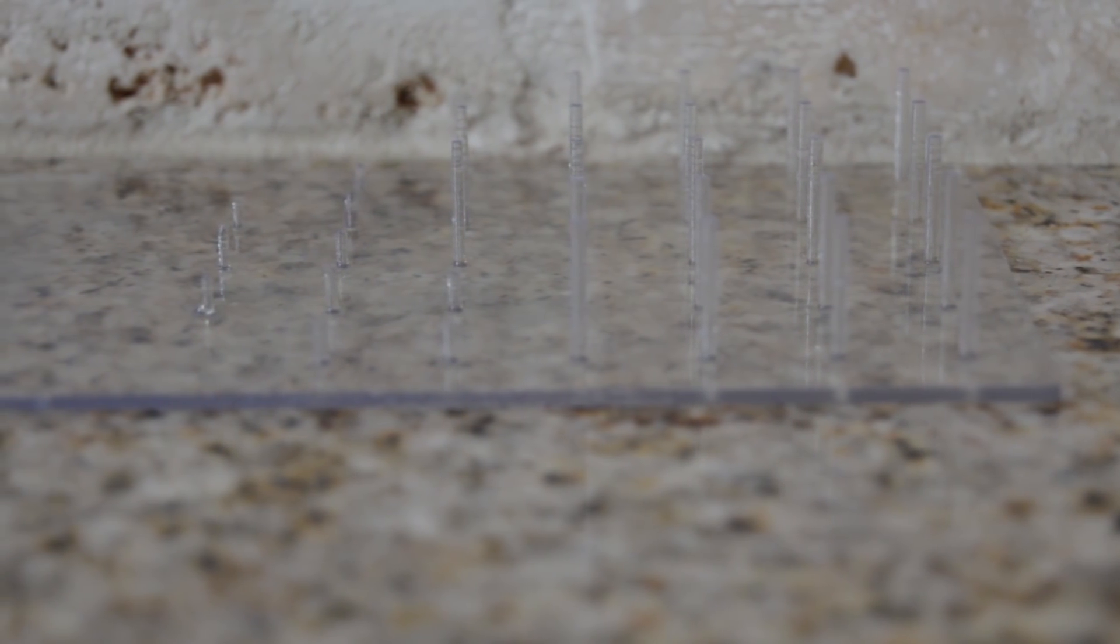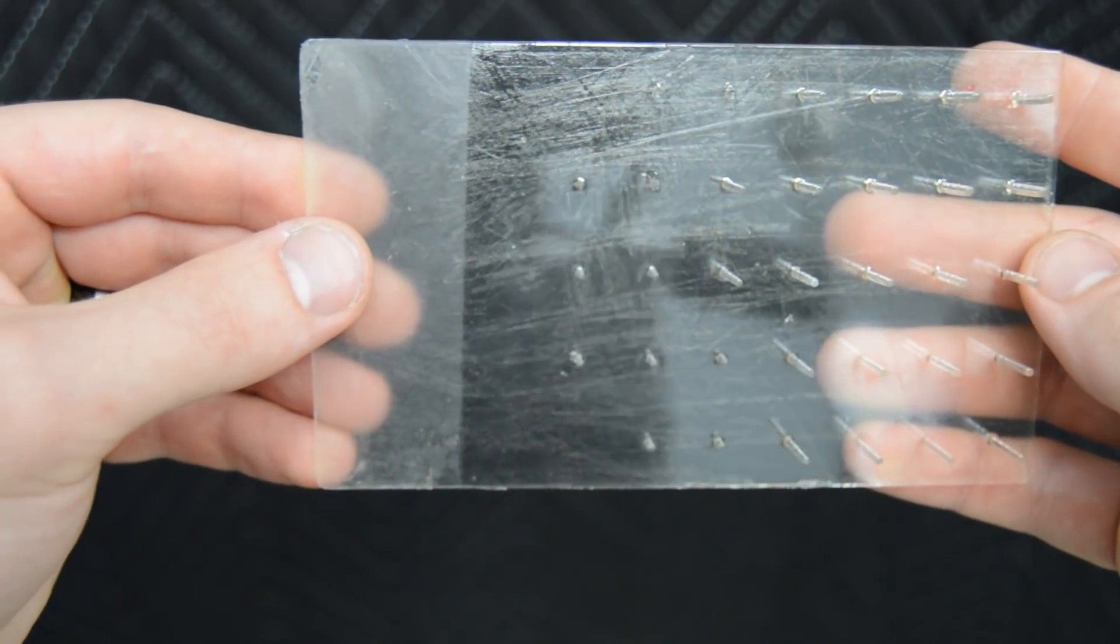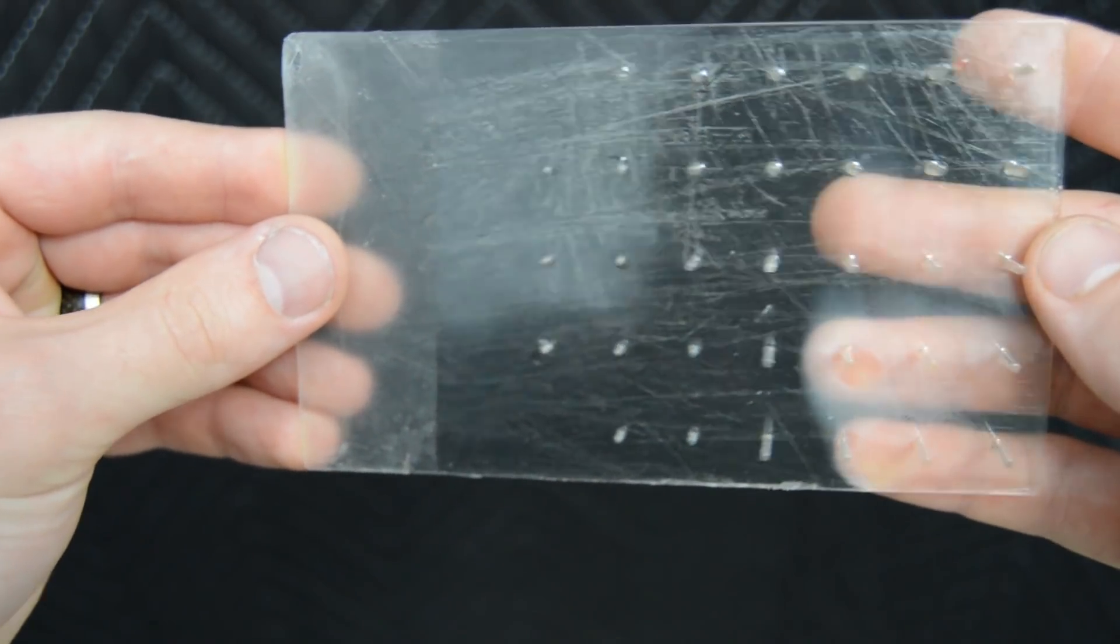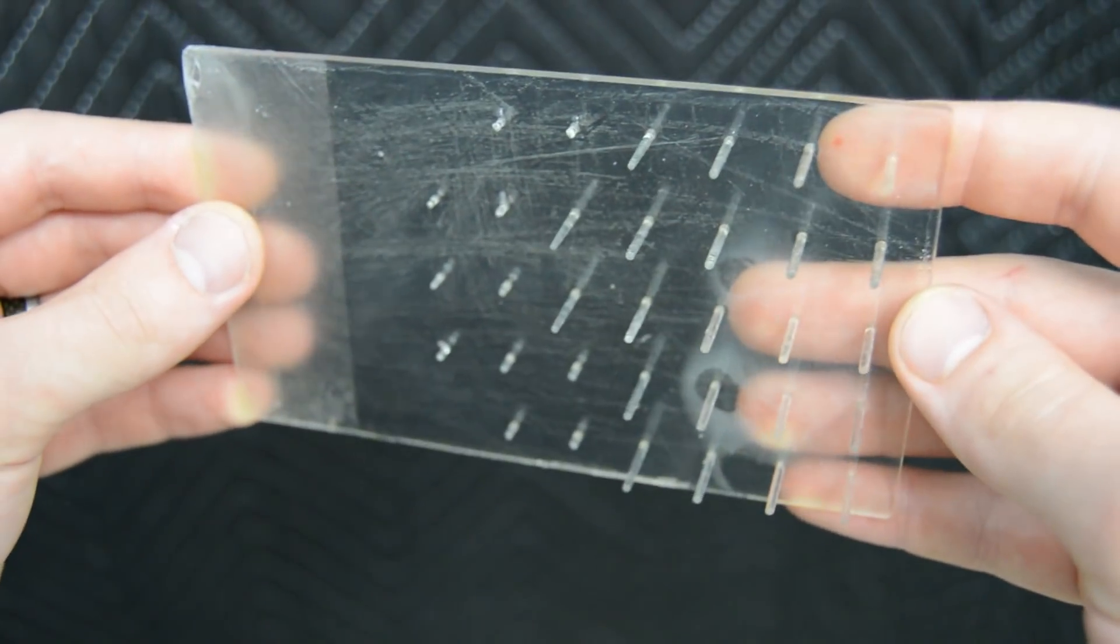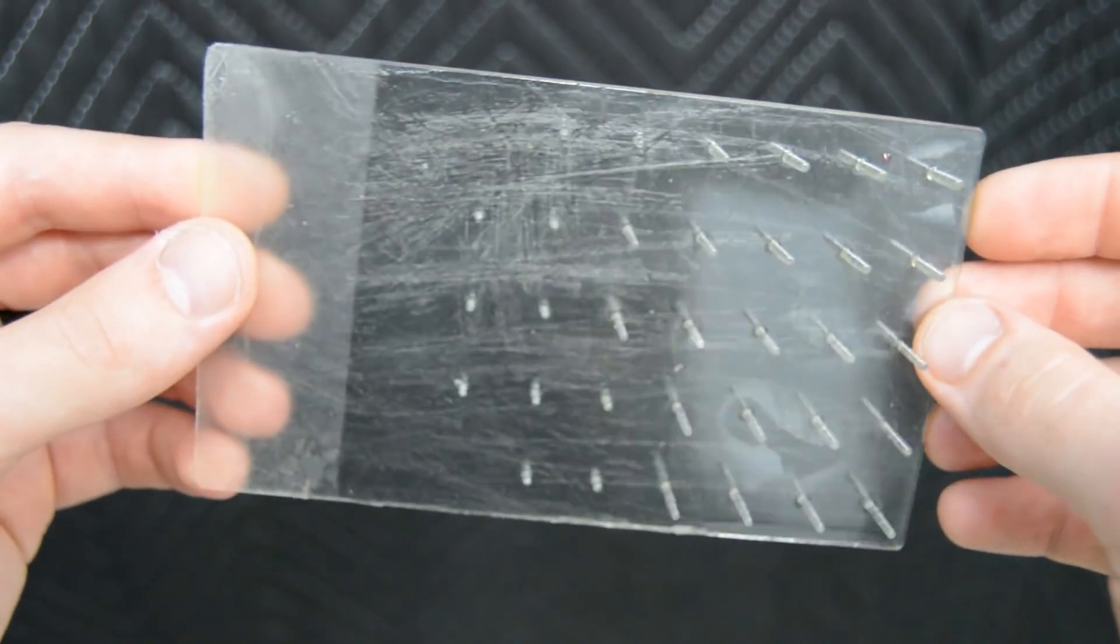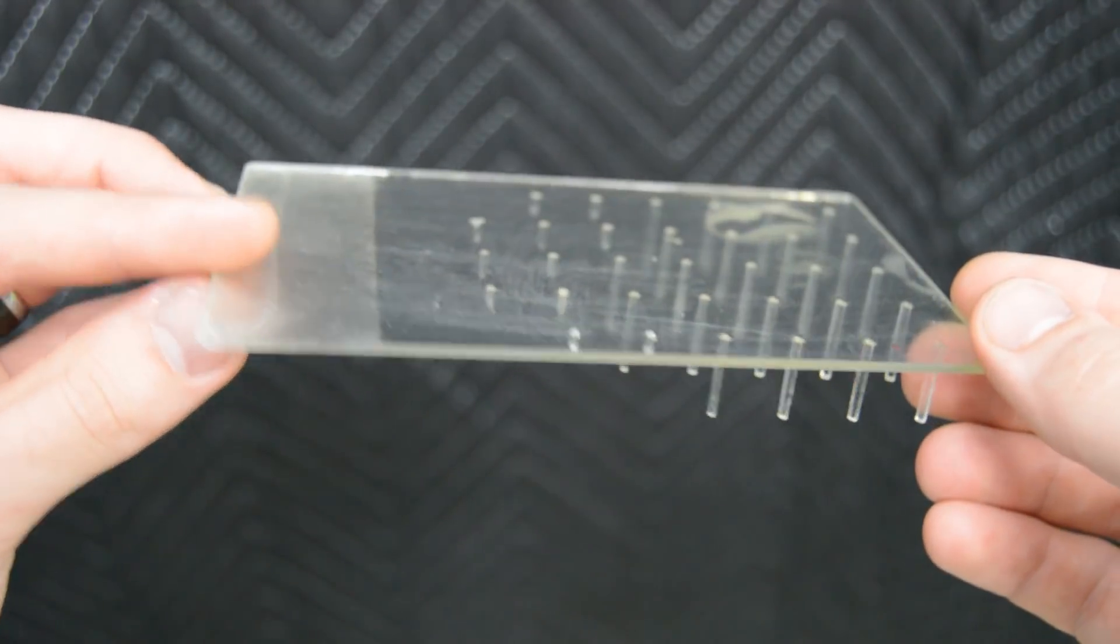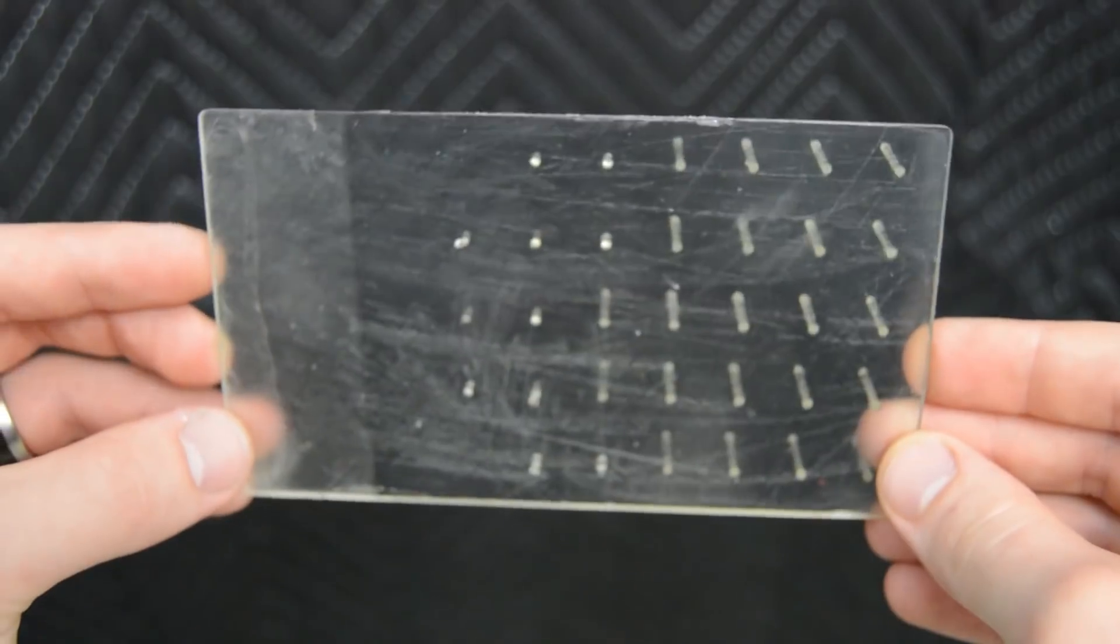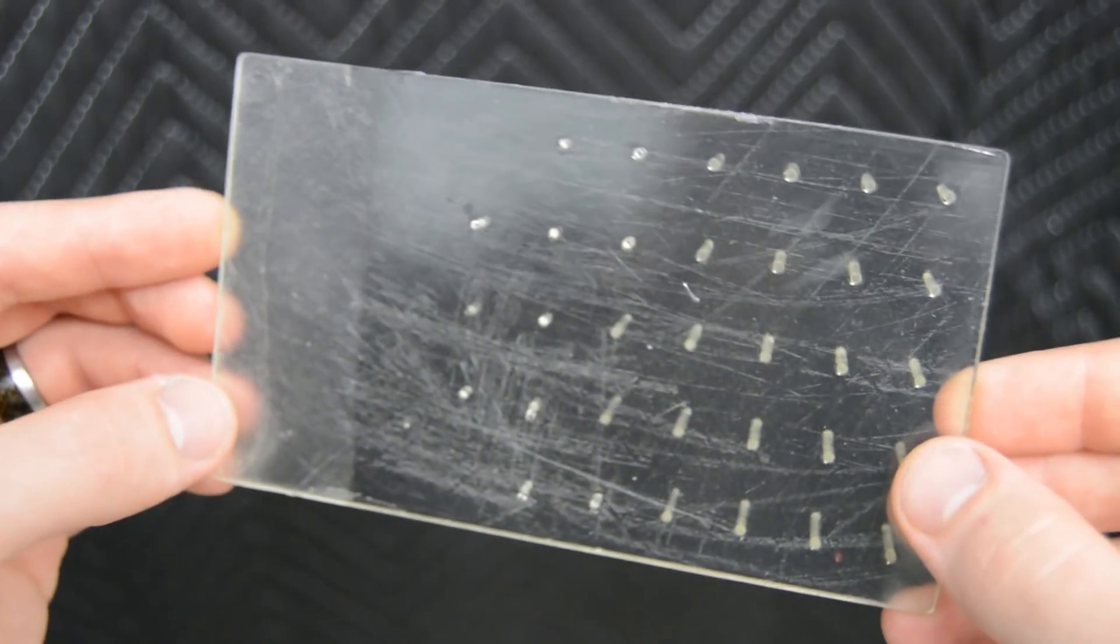What you'll see is that I dipped about 80% of it in the polycrylic and it came out looking really clear. The other side looks just a little clouded, and that's because the plate here was directly on the build plate, so all the scratches from the build plate were transferred over to the part.